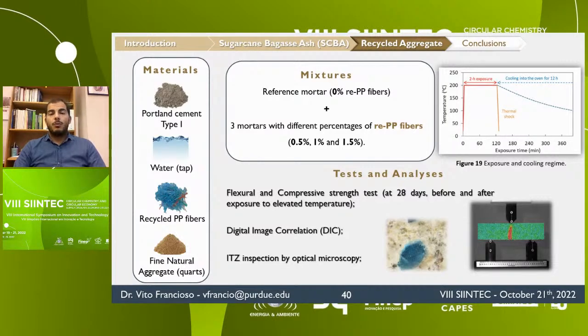The samples were exposed for 2 hours at 200 degrees Celsius, and then they were tested after 2 different cooling regimes: thermal shock, meaning that the samples were tested right after the 2 hours of exposure, and then after 12 hours cooling in the oven.